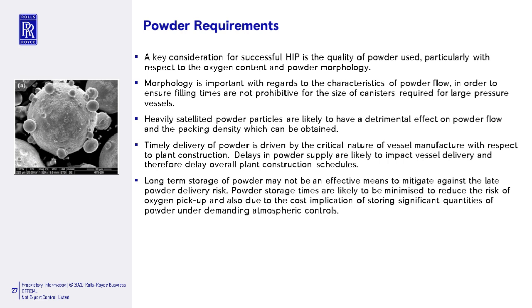Key things to consider with powder then. There's a little image on the left hand side there, but we've done quite a lot of work previously and also more work recently on the quality of powder. The quality of powder into the process is paramount to getting a good product out of the process. Particular things that we need to control are oxygen content and the actual morphology of the powder itself. So the morphology needs to be right, because the critical point here is how you fill your canister. So you need to get uniform powder flow, and you need to get really good packing within that canister so that your HIP process gives you a high quality part at the end.